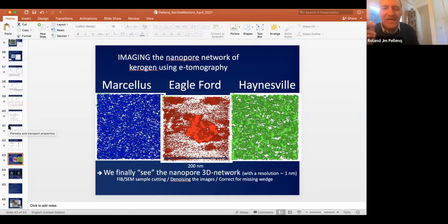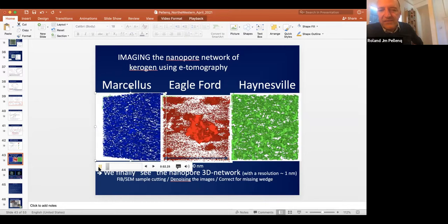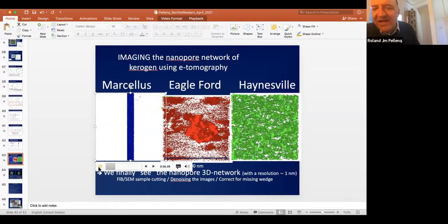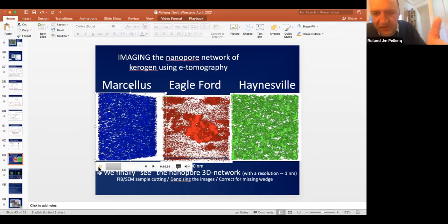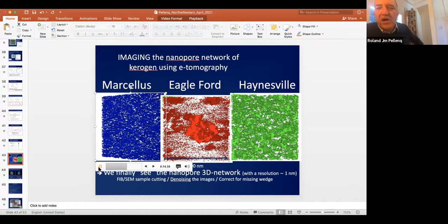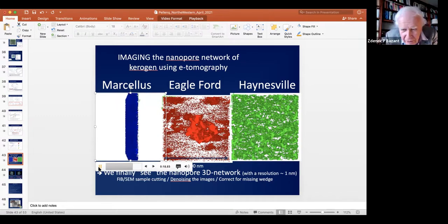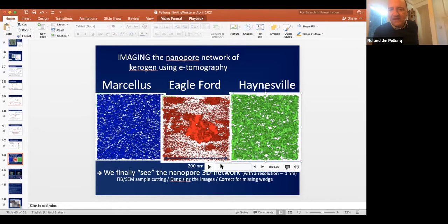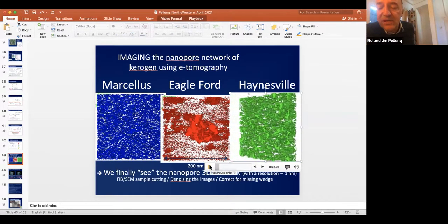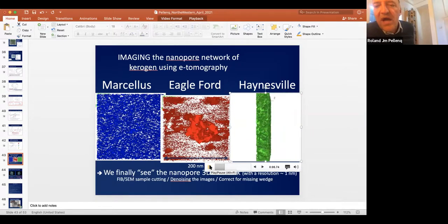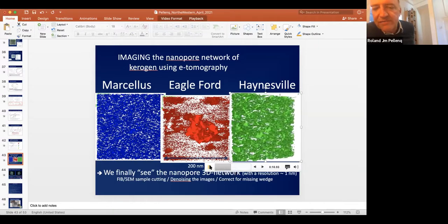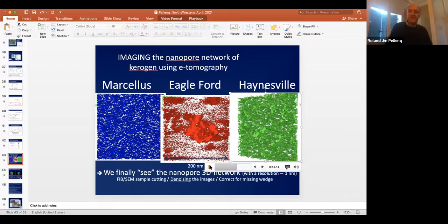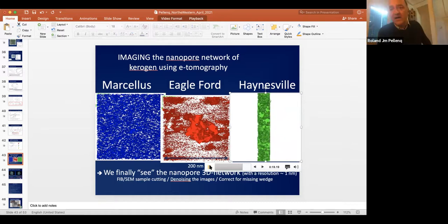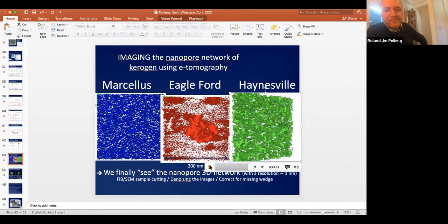Now, what I cannot answer is whether they noted the orientation of the sample. What I can tell you is that if you do tomography on the Marcellus, you see no orientation of the pores. At that scale there is no particular orientation of the pores, at least for the super nanopores. They are in all directions in 3D. Haynesville is the same thing. Haynesville is a mature kerogen, a bit like Marcellus. What we see is at least one nanometer pores, which is the lowest they can resolve, and you see that the pores are in all directions. There is really nothing particular. But yes, in simulation we can actually play around with an anisotropic pressure field. Okay, thank you.